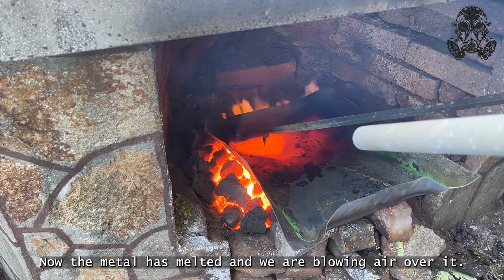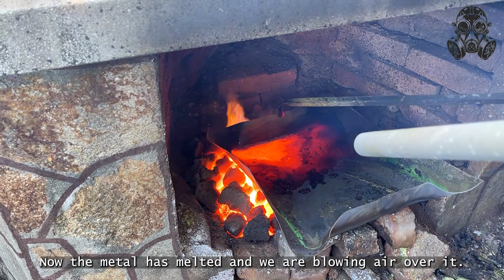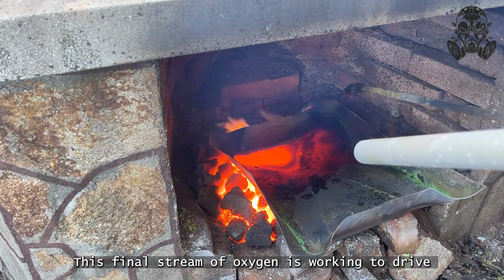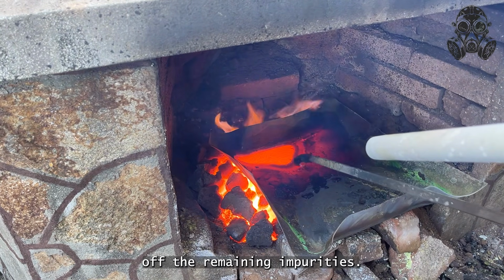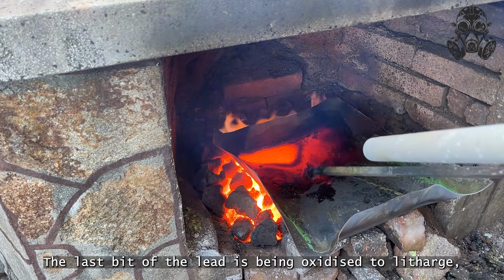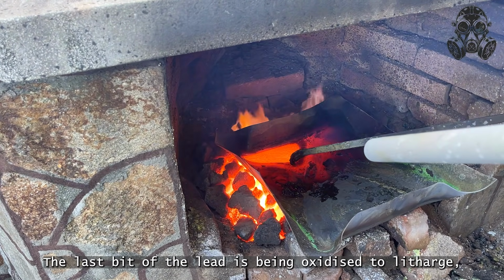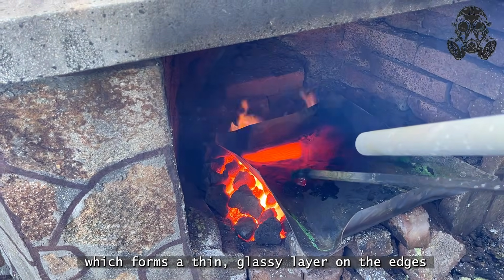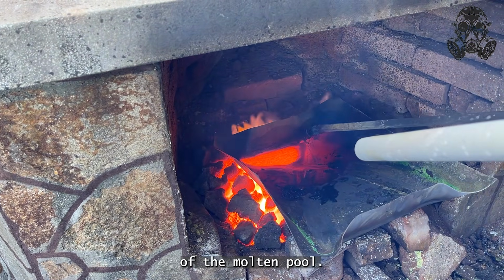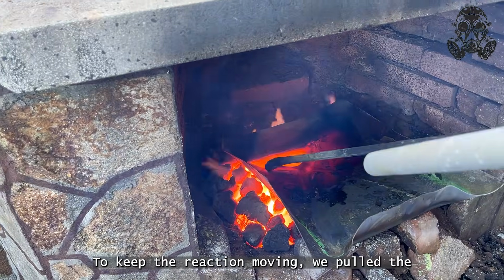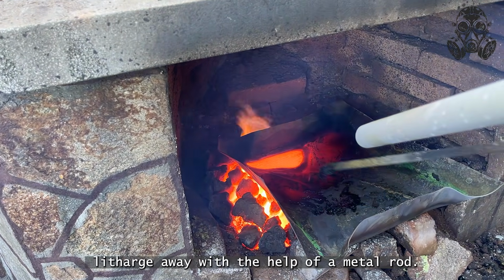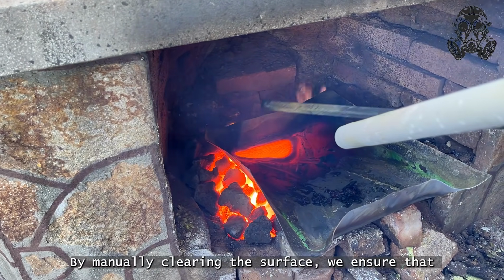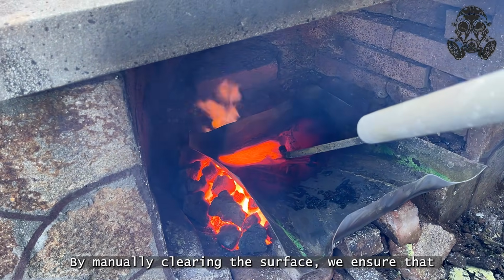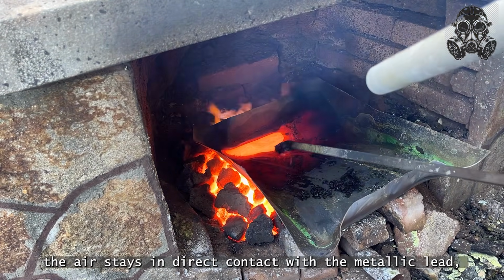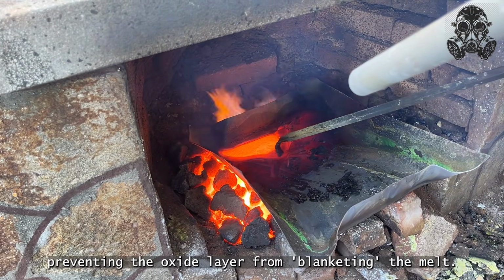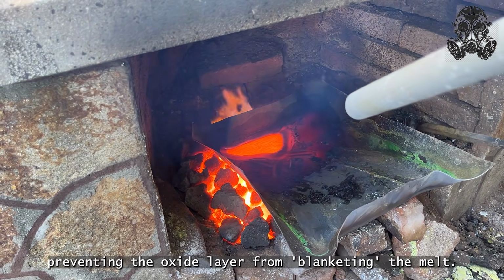Now the metal has melted and we are blowing air over it. This final stream of oxygen is working to drive off the remaining impurities. The last bit of the lead is being oxidized to litharge, which forms a thin, glassy layer on the edges of the molten pool. To keep the reaction moving, we pulled the litharge away with the help of a metal rod. By manually clearing the surface, we ensure that the air stays in direct contact with the metallic lead, preventing the oxide layer from blanketing the melt.